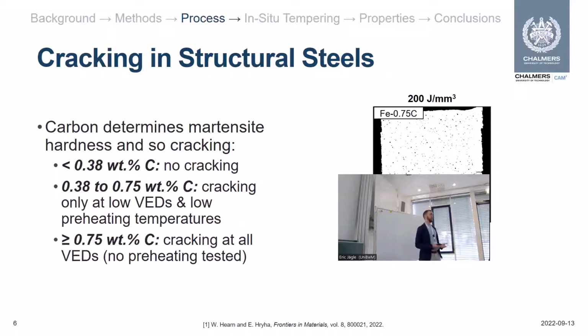And the in-situ tempering provided by build plate preheating is quite straightforward to understand. You're just having an elevated ambient temperature during processing. This helps to both relieve residual stress as well as improve tempering of your martensitic structure.